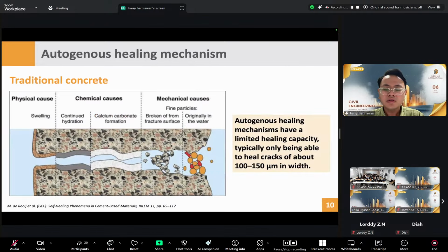Then, regarding the autogenous healing mechanism in traditional concrete, there are several causes. If you look from the left hand side, there is a physical cause, which is due to the swelling process. Concrete in general will either shrink or swell. If your concrete mixture is designed to swell, the swelling of the matrix will also later lead to crack closure. Next, with regard to the chemical cause, autogenous healing can occur due to the continuous hydration of the cement or from the formation of calcium carbonate, CaCO3 as a chemical notation.